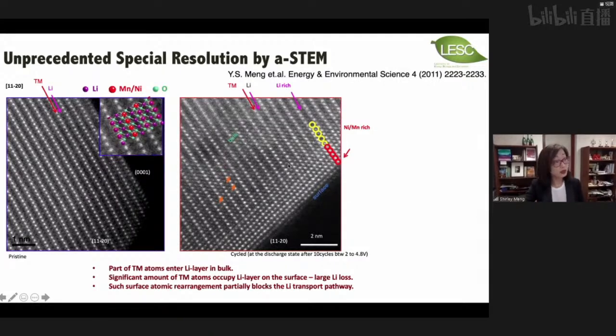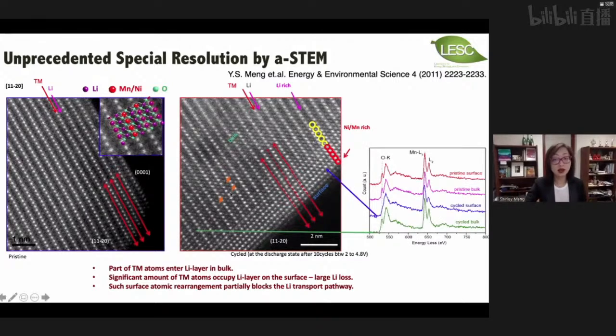And the change is very subtle. After high voltage exposure, you actually see the lithium and transition metals swapping their positions, but the major phase change is only on the surface, 2 nanometers, right? And this phenomenon can easily be missed by traditional diffraction-based techniques, but with this kind of new fancy tools, we can then detect the structural and chemical change on the high voltage cathode materials. And since then, the entire battery field has always known the cathode particle surface has to be protected with some kind of very robust coating so that the battery can operate a long time at high voltage.